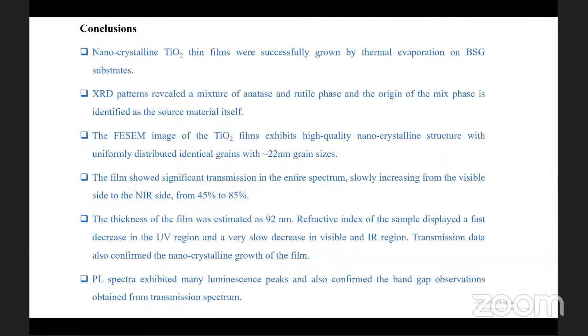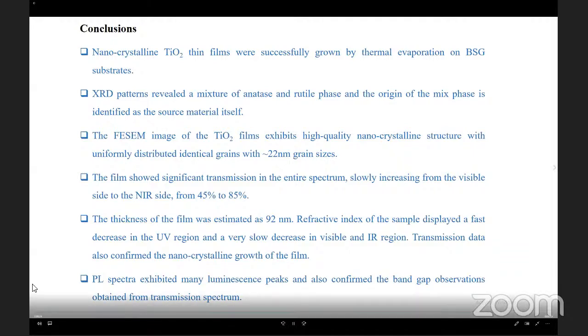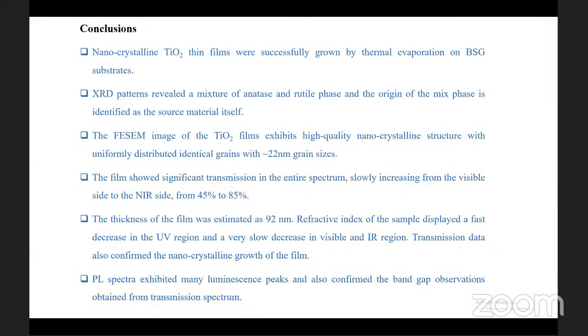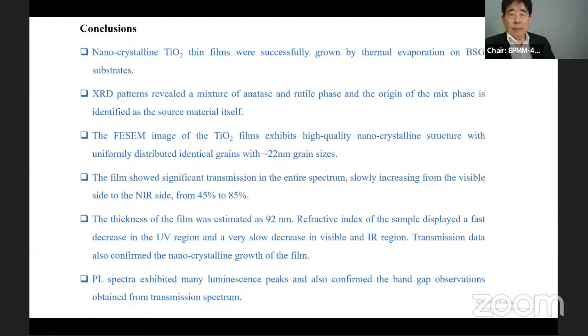The film showed significant transmission in the entire spectrum, slowly increasing from the visible side to the NIR side, from 45% to 85% transmission. Thickness of the film was estimated as 92 nanometers. The refractive index of the sample displayed a fast decrease in the UV region and a very slow decrease in the visible and IR region. Transmission data also confirmed the nanocrystalline growth of the film. PL spectra exhibited many luminescence peaks and also confirmed the band gap observations obtained from the transmission spectrum.